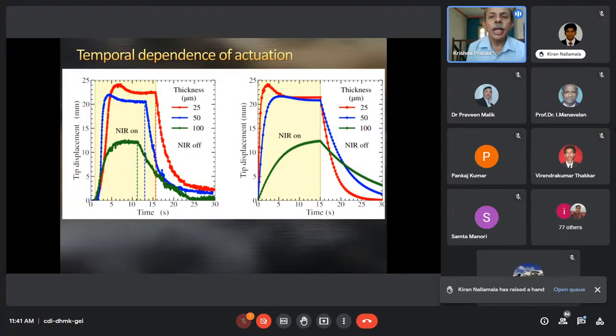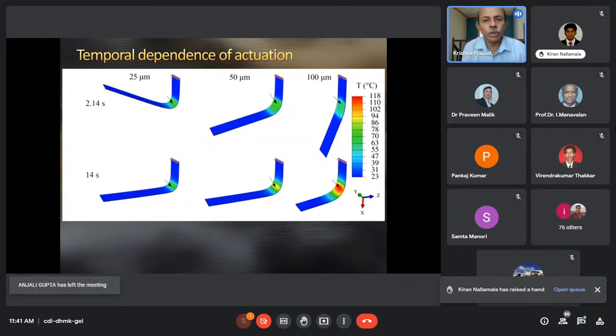Quantitatively, again, on the left you have the experiment, on the right you have the simulations. Both of them compare very well, and we have been able to achieve very large displacements, something like 20-25 mm actuations taking place in the medium. The magnitude as well as the response of the system depends strongly on the thickness of the film, and that's what I have shown here. Response times can be counted in seconds in very thin films, and so you could have a very good actuator coming from such NIR-driven systems. For the details of the simulations, I won't get into the detail here.